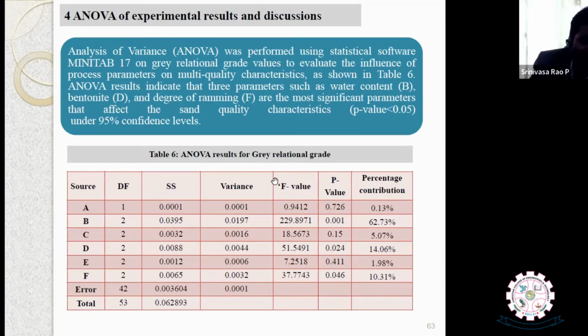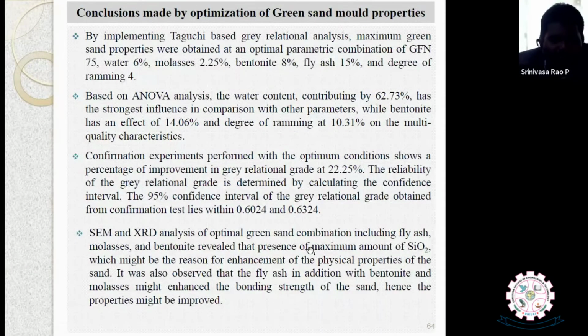So we may add many other materials like bentonite clay, corn flour, coal powder, or fly ash, and so many other products, but water, moisture, plays a very important role, because that is the binder basically. The optimal process parameter combination we have got is grain fineness number 75, water percentage 6%, molasses 2.25, and this is the optimal composition. Based on the analysis, water content contributes 62.73% as the strongest influence in comparison with the other parameters. Later, confirmation experiments were carried out, and we found that the grey relational grade improved by 22.25%. Then we carried out XRD analysis.